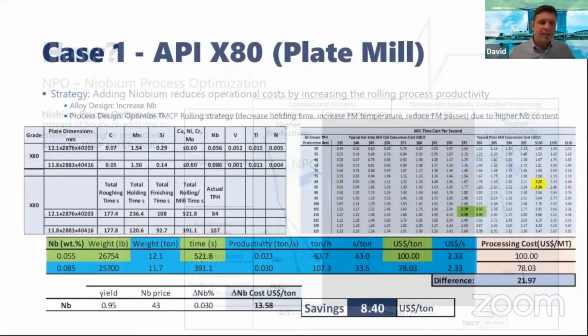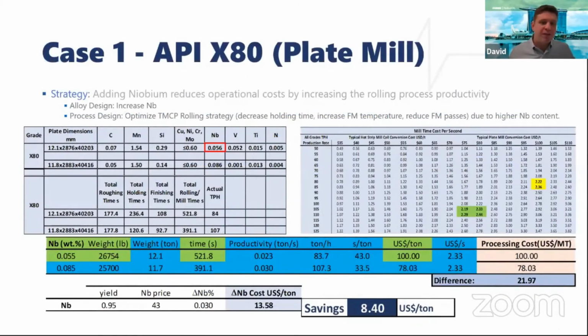The first example is an X80 pipeline steel produced in a plate mill. And the first alloy design had 0.056 niobium with 0.05 vanadium addition. And the productivity was about 84 tons per hour by respecting the amount of niobium, the recrystallization process for a proper TMCP of an API high strength steel.